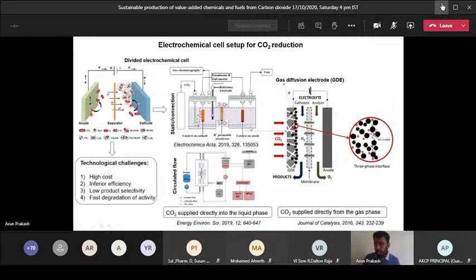The other one is the electrode. Carbon dioxide is a gas, so you have to feed this gas into your electrolyte, and the solubility of carbon dioxide is a major issue. So people use highly soluble solvents like methanol. But if you want to produce methanol in your system, then you can't use methanol as your electrolyte. Obviously, you have to use an aqueous electrolyte like bicarbonate solution. You can feed the carbon dioxide into the solution at your working electrode, but carbon dioxide will not dissolve easily. Alternatively, you can use a gas diffusion electrode. Instead of purging the carbon dioxide into the electrolyte, you can purge it into the backside of your electrode, which has a lot of pores.